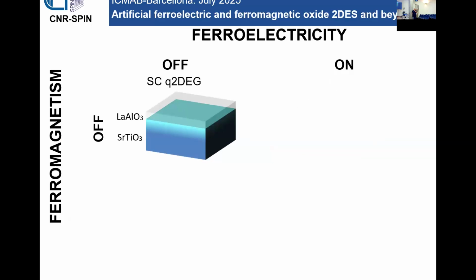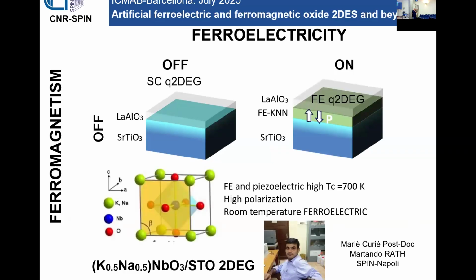Now, coming more to the new results, the problem of calcium-doped STO is that the TC is 25 to 30 Kelvin maximum, and the ferroelectric polarization is relatively low. So it would be much better to have a system where the polarization is much larger and possibly with room temperature ferroelectricity. So another approach is to use another layer, a ferroelectric layer deposited between lanthanum aluminate and strontium titanate, and try to get a two-dimensional electron gas and couple the polarization of the ferroelectric to the properties of the 2DEG.